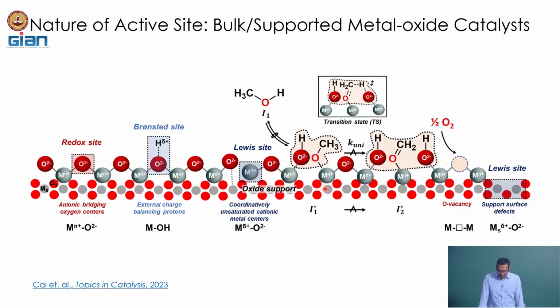And it can happen that some of these sites are giving us the favorable product, and some of these sites are giving us the undesired product. So, as a matter of fact, we need to know which sites are giving us the selective product and which sites are giving us the unselective product. And once we figure that out, we can populate the surface with the selective sites and suppress the unselective sites. And for that, we need to know the structure activity relationship, which is the essence of catalyst design. And to understand that structure activity relationship, we need to understand how the catalyst functions. And that is how this course is defined.